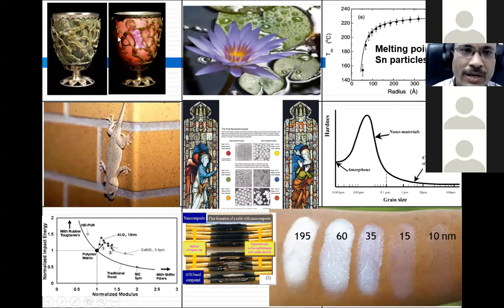Now you see on the left side, as I have already told you, the Lycurgus cup, made around 2000 years ago, made of a glass matrix. The only difference between this glass and the glass we have in windows is that this glass consists of ppm level copper, gold, and silver nanoparticles. The size is below 50 nanometers. Because of that, you can see the color is different in reflection mode and transmission mode.